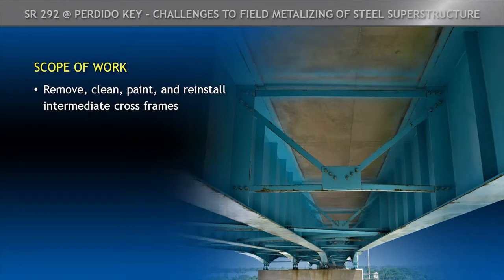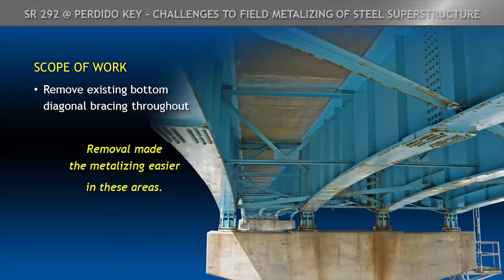We removed, cleaned, and coated the intermediate cross frames. This made sure that we got rid of all the pack rust, got into all the nooks and crannies, and made it a lot easier to ensure we're going to achieve the service life of the product. The lower lateral bracing we actually removed completely from this bridge and did not reinstall. This made it a lot easier to get the proper coating.